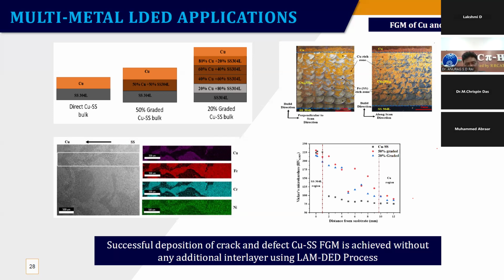You must be appreciating this when you have a functionally graded material like copper and SS, where the coefficient of thermal expansion is pretty large, and they see a temperature difference and a change of temperature during service. Then what is going to happen is the copper will go its way, and SS will go its way. And we all know that the coefficient of thermal expansion for copper is much higher than SS, and it puts a lot of stress at the interface, and the components are likely to fail from there.